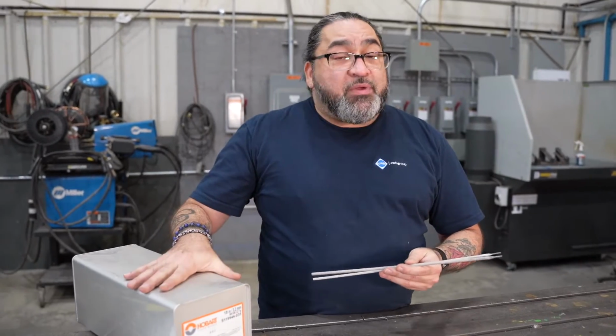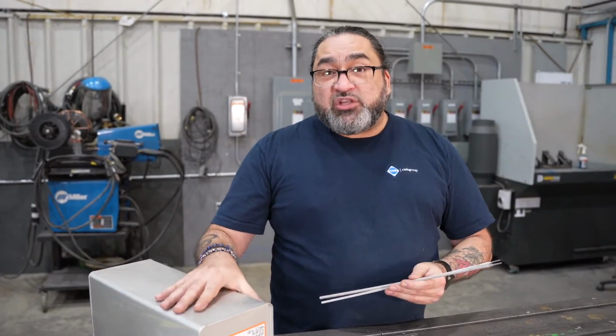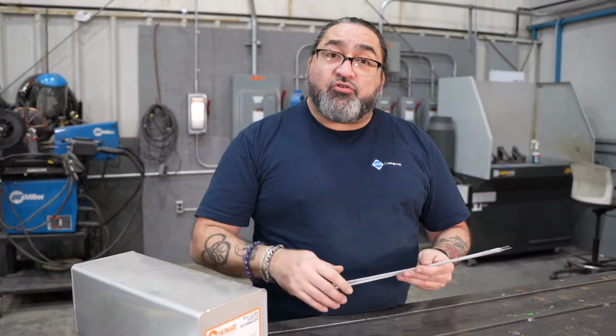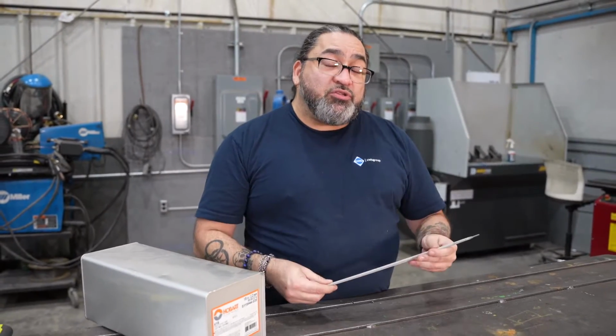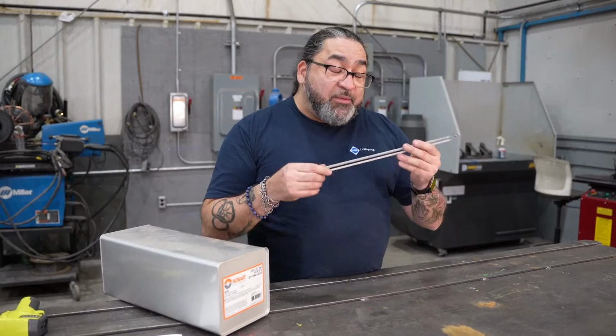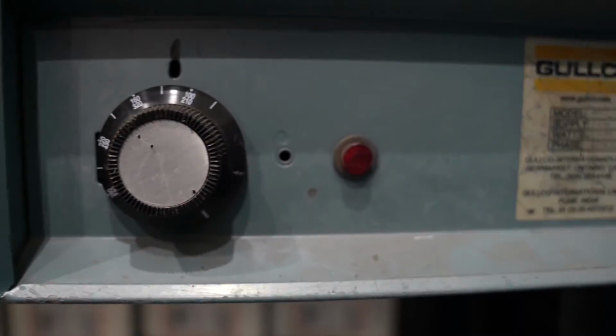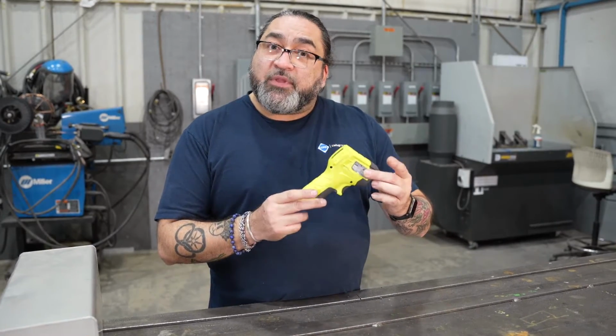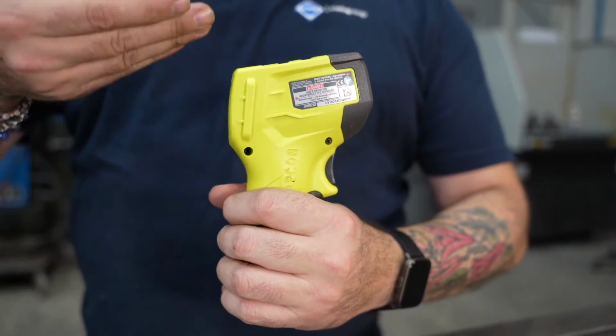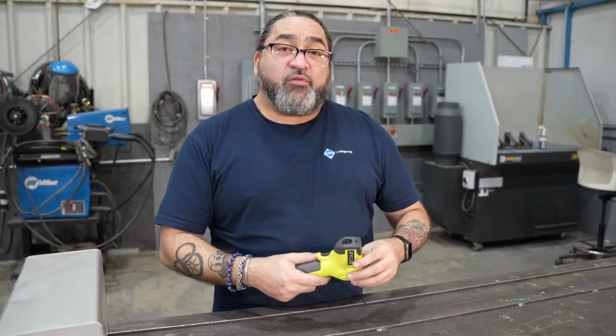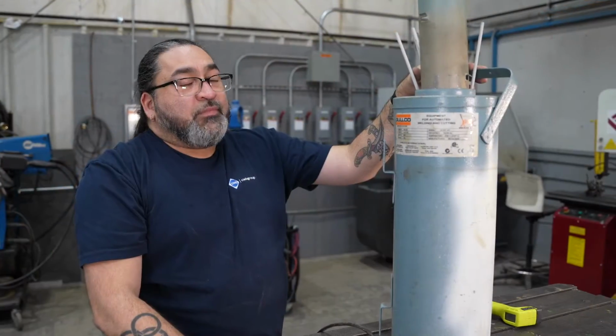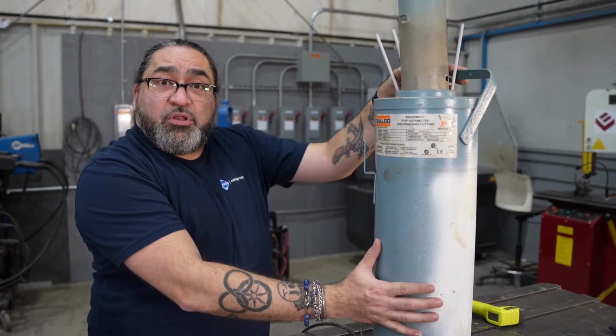Now, if they stay in the hermetically sealed box, that's okay for transport and moving them around, but as soon as you crack that seal, they must be put into a hot environment that reaches a minimum of 120 degrees Celsius. One of the easiest ways to check your rod ovens and make sure your rods are to the right temperature, which is 120 degrees Celsius or 250 degrees Fahrenheit, is with a digital temperature checker. They're a low cost, easy to use tool that you can find at most hardware stores or order from your local supplier.